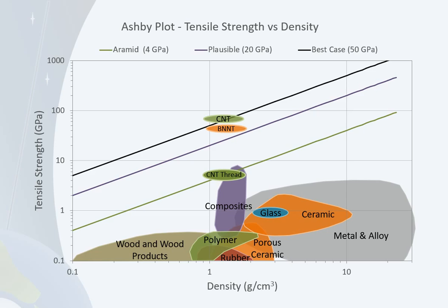That's really all there is to say. Further, they tend to have a low density. You find that about 1 gram per cubic centimeter, which is comparable to water. So they're really at a nice sweet spot with a low density, very high tensile strength. And for the record, the numbers I'm using on this plot, none of these are theory. These are all empirical, tested measurements. Someone made this material and put it on a tensile testing machine. They weighed it, they measured it, and that's how we got these numbers. There are some pure theory stuff that exceed this, but this is all real data, all real materials.